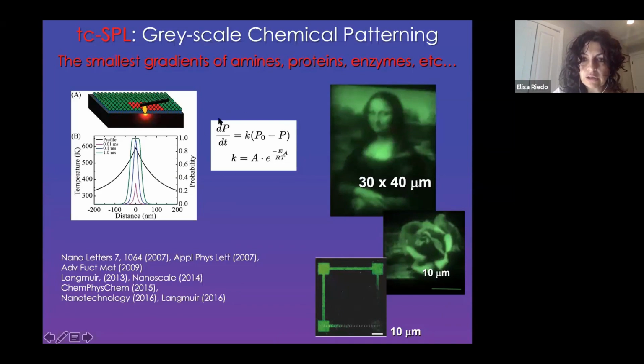Then for this type of chemical reaction, we can write the equation of how the probability of the reaction changes with time. And it follows a first order chemical reaction equation, with k being the rate of the reaction. So when you put the two equations together, you can see that by varying the temperature, T, or by varying the variable of time. What is time? Time is the dwelling time, meaning the time that your tip stays in contact with the surface. So the longer you stay in contact, the higher the temperature, the more probable it is that the chemical reaction happens. The faster you move, the less time you stay in contact, the less probable is the chemical reaction. So everything is inside here, so it can be very nicely analytically predicted.